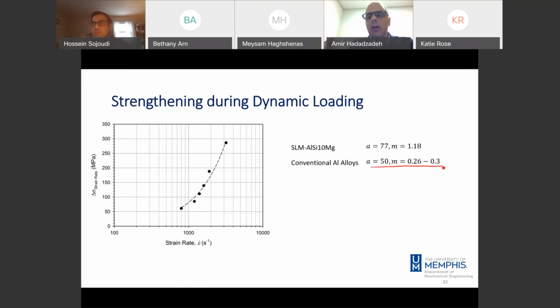For conventional cast aluminum alloys, I was able to find the values from literature. If I plot that here, we have a graph something like this, and probably something over here. So there's a difference in terms of the effective strain rates and the strength increment in two cases.